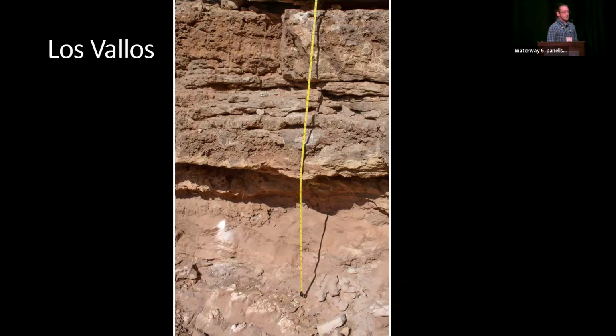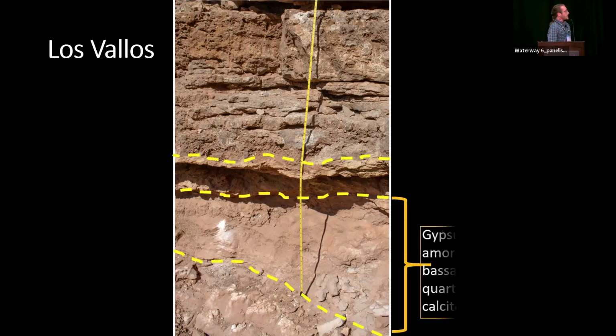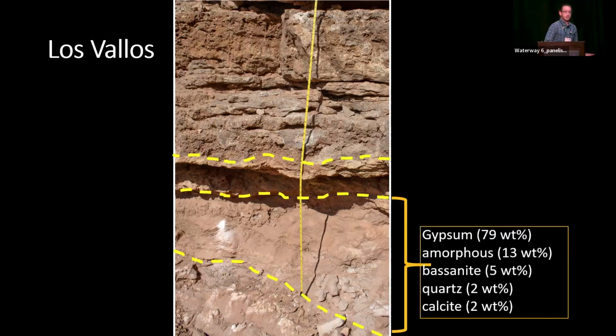Over at the Los Vallos outcrop, first of all, it's a much larger outcrop. It's about 6 feet tall. But it also breaks down into 3 main zones. Again, the lower zone is very gypsum rich. It's about 79 weight percent gypsum, some amorphous material, a little bit of bassanite. A tiny bit of calcite, about 2 weight percent, which we suspect is contamination from all of the limestone dust that's blowing around in this area from all of the limestone.